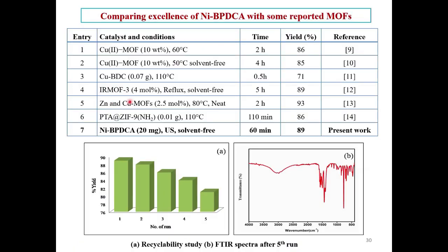Comparison of the excellence of nickel BPDCA with some reported metal organic frameworks. Here the time required is 60 minutes, here it is 2 hours, 4 hours. Here the temperature is very high. With the help of the ultrasound cavitation technique in solvent-free condition, there is no high temperature. We have done it in 60 minutes with 89% yield.